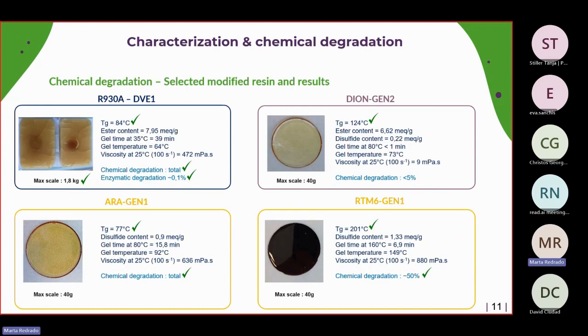For the 4 resins, different processes and iterations were carried out to modify them. We based these modifications on the thermal properties, which are quite important, especially the Tg, the glass transition temperature, which had to be as similar to the reference resin as possible. Here you can see, for each type of resin, one that we developed in the project. We also studied rheology as well as the chemical degradation. As you can see here, for the R930 and the Aragen, the chemical degradation was total for both resins. It was 50% for the RTM6, and for the dione it was 5%. It has also to be noted that for the R930, some enzymatic biodegradation was also seen.